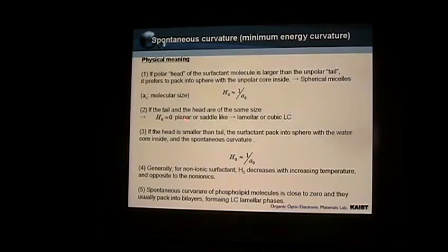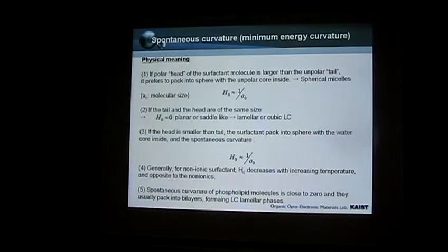So H0 is 0, planar or saddle, that forms lamella, or the sponge phase, or the cubic crystal. And if the head is smaller than the tail, the surfactants pack with the water core inside, and they also have some particular spontaneous curvature like that, right? So in this case, this is the spontaneous curvature, which is the minimum energy. Here the head is smaller than the tail, and this is the spontaneous curvature which is minimum energy. So generally, for non-ionic surfactants H0 decreases with increasing temperature, and the opposite for ionic.